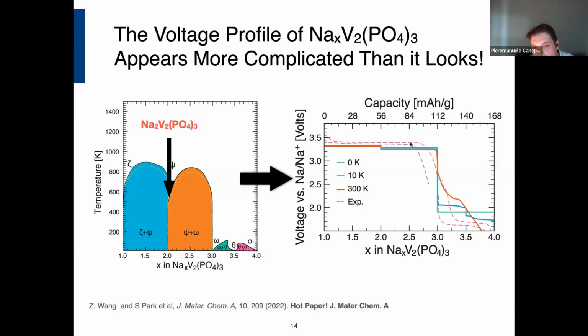So here the voltage curve is flat, you don't see this step, so what's the deal, right? Now, this gave a hint to our experimental colleagues. Well, they said, if the theory people see a single phase region at x equal 2 from the phase diagram, maybe it's possible that if we combine at high temperature a synthesized Nasicon at composition 3 and a synthesized Nasicon at composition 1 in the proportion of x equal 2, we might be able to form this phase.